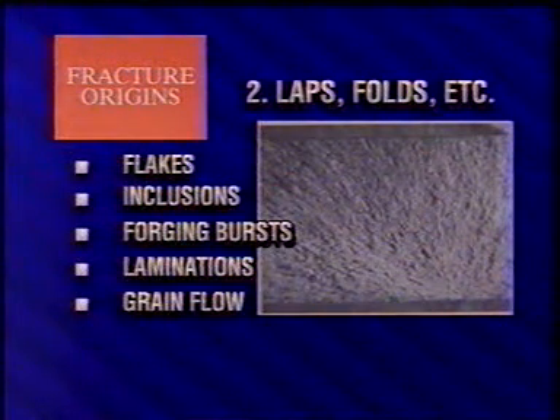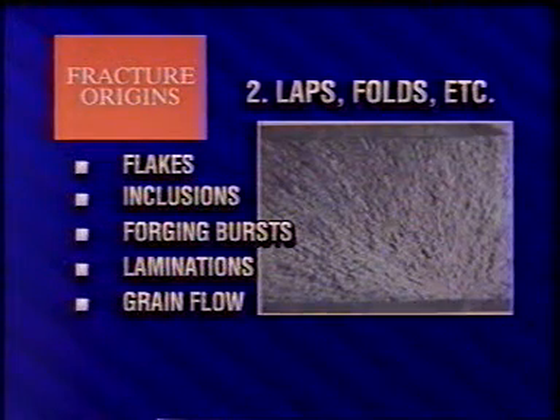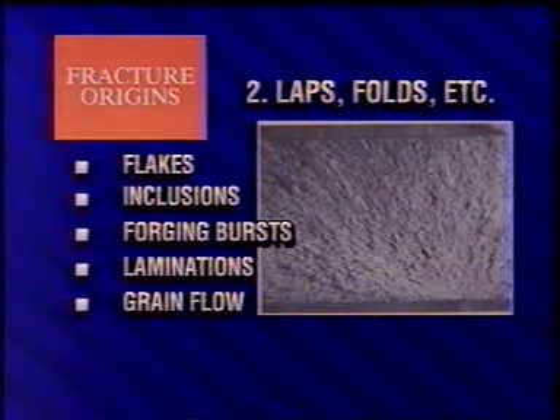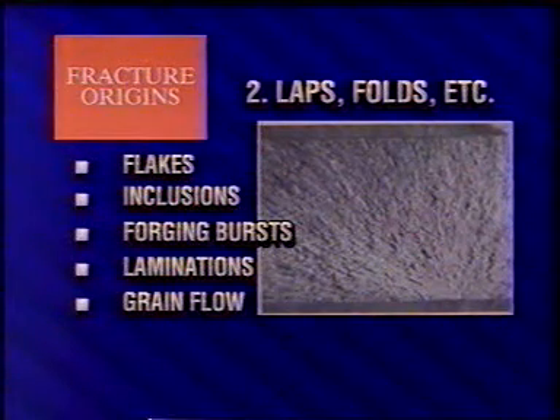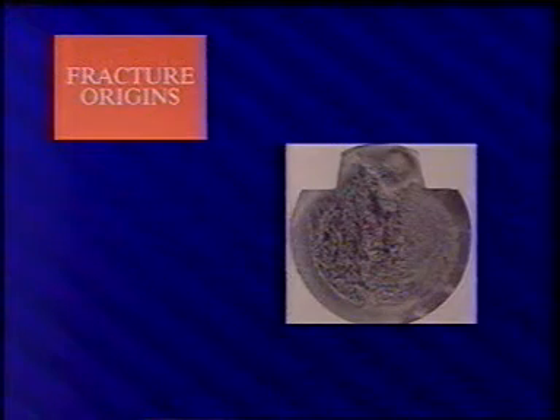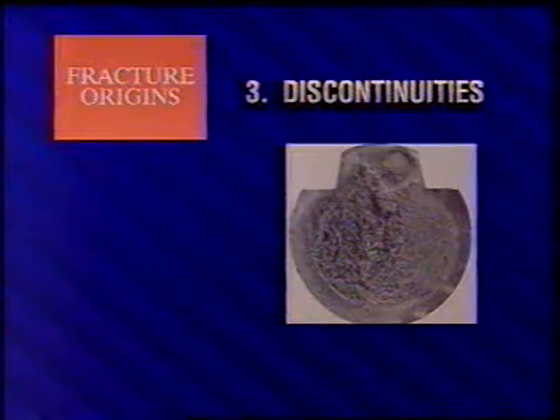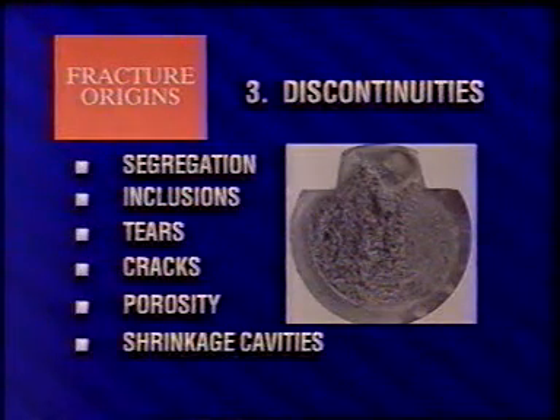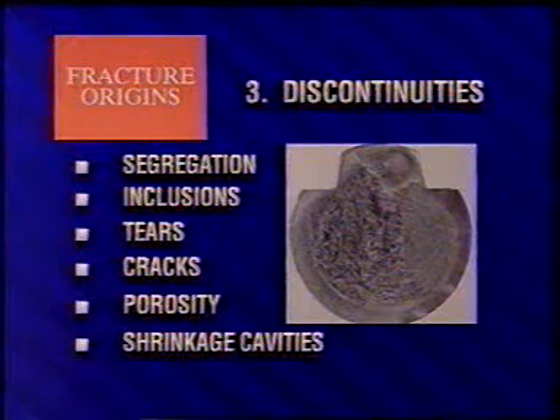The second form of initiation area results from laps, folds, flakes, large inclusions, forging bursts, laminations in sheet and plate, and undesirable grain flow introduced during working operations. All these may influence the location of fracture origin. Third, factors causing stress concentrations may lead to failure. Certain discontinuities, such as segregation, inclusions, tears, cracks, porosity, and shrinkage cavities, can have serious consequences, particularly in castings.